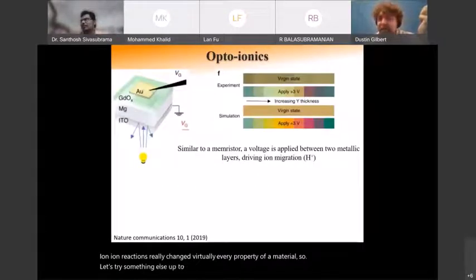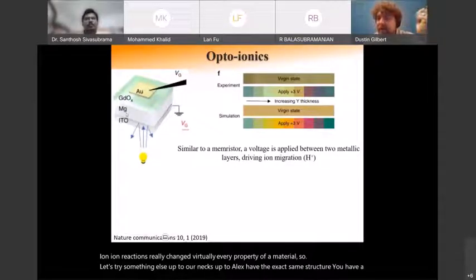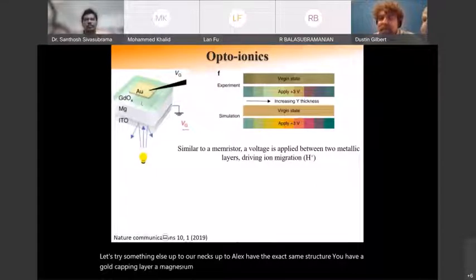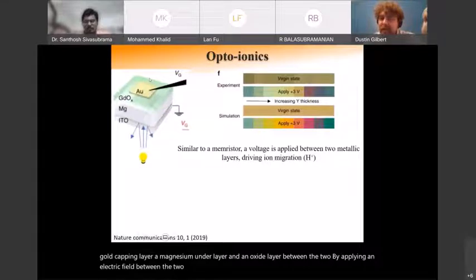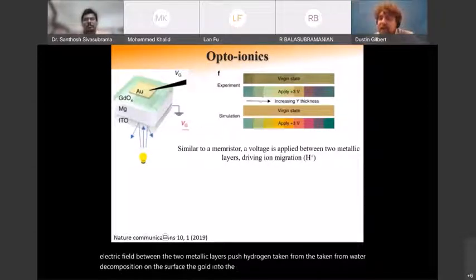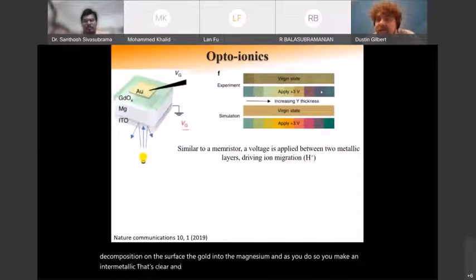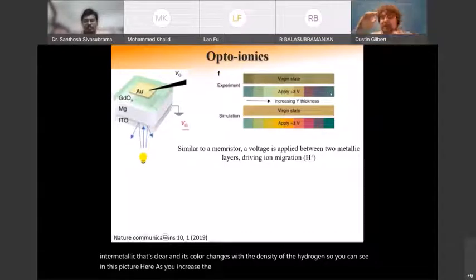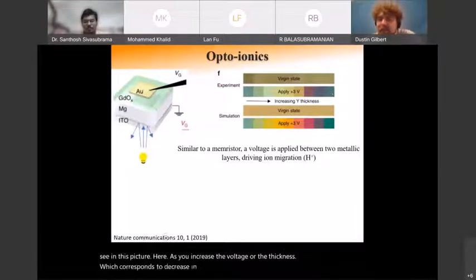Optoionics. Optoionics have the exact same structure. You have a gold capping layer, a magnesium underlayer, and an oxide layer between the 2. By applying an electric field between the 2 metallic layers, you push hydrogen taken from water decomposition on the surface of the gold into the magnesium. And as you do so, you make an intermetallic that's clear, and its color changes with the density of the hydrogen. So you can see in this picture here, as you increase the voltage or the thickness, which corresponds to a decrease in hydrogen density, you go through the whole spectrum of colors.